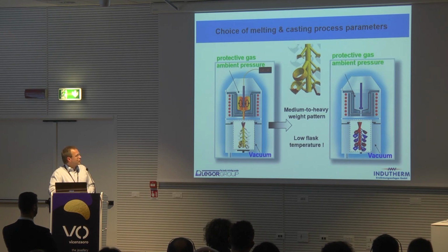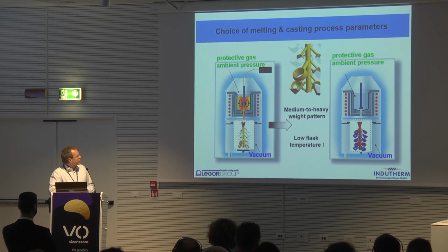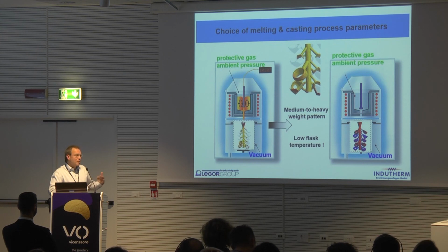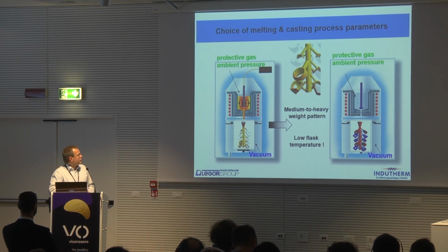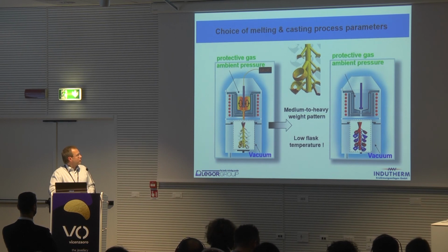More heavy parts will be more prone to gas porosity caused by reaction with the investment. So it's always a good idea not to exaggerate, not to put a vacuum also in the upper chamber here. We will just maintain an ambient pressure in the melting chamber. This will create only a partial vacuum then in the inside of the mold. So when the metal pours in, the metal flow will be more gentle. There will be a back pressure on the molten metal when it is pouring inside the mold. This will reduce turbulences, and it will lead to less reaction with investment. In combination with a low flask temperature, this is a good idea to avoid reaction with investment.